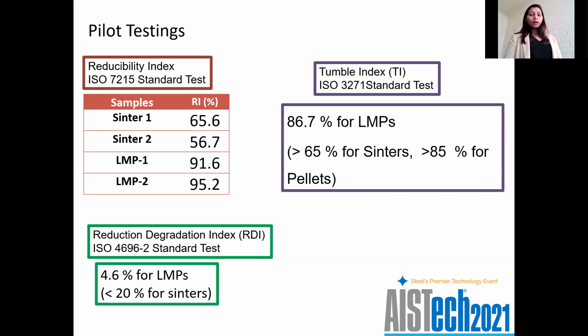Now for RDI, we do the reduction in the same CO nitrogen ratio and same flow rate, but the temperature is 550, reduced for half an hour. After that the reduced pellets are tumbled at 30 RPM for 900 revolutions. Then the products are sieved, and the minus 2.8 size fraction is called RDI. For the LMPs, the RDI was found to be 4.6 percent, and the acceptable RDI for sinters is less than 20 percent. For pellets, usually the papers report about 5 percent plus minus. So the LMPs have a similar RDI to pellets as well, and much better than the sinters.